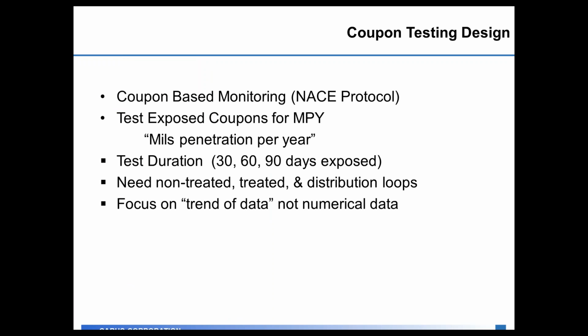There's some other things you can look at if you're picking a phosphate product for the first time or you want to monitor what your current program is versus a new treatment change. You can do coupon-based monitoring. This is the NACE protocol, National Association of Corrosion Engineers, and what you're looking at is putting test coupons out in the system and looking for how much of that coupon erodes over the course of a year in the case of mils penetration per year, or MPY.